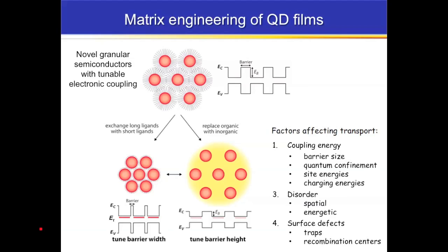So we can tune coupling and tune charge transport in this kind of film by doing one of two things. We can either make the barrier thinner by replacing the long chain organic with a short chain molecule or inorganic ligand. And that's going to make the barrier thinner. That will enhance coupling. The other thing we can do is replace this organic material with an inorganic matrix, indicated by this yellow stuff here. And if we choose that inorganic matrix correctly, we can lower the barrier height without really changing the barrier width, and that will also improve coupling between the dots.